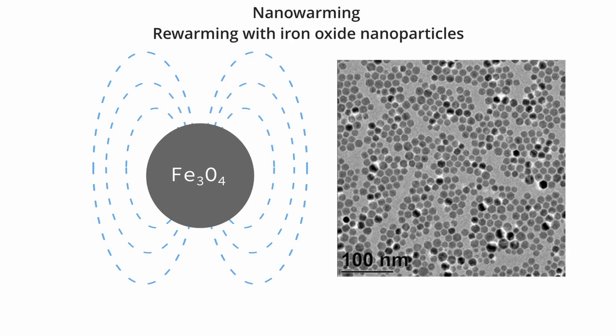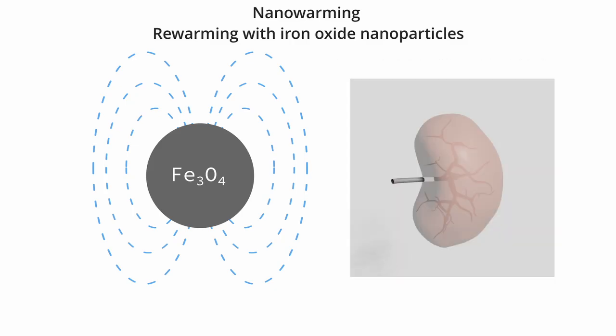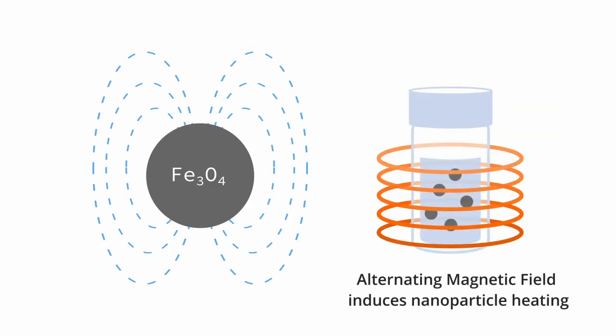Nanowarming is a novel technique that addresses this issue by increasing the rewarming rate through usage of iron oxide nanoparticles, which are evenly perfused into organs to be cryopreserved. Iron oxide nanoparticles are commonly used as heat sources via irradiation by an alternating magnetic field in the radiofrequency range.